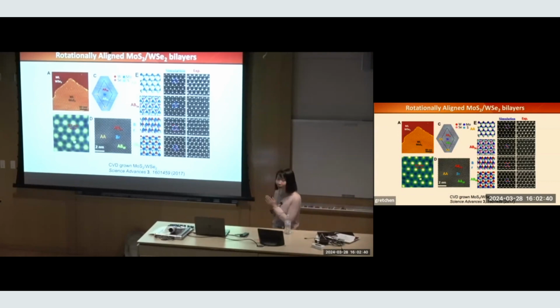But people can grow them on wafer size. And when you grow them, these two materials have different chalcogenide atoms. Because of that, the lattice constants differ from each other by a few percent. When they grow, they tend to align the crystal axes because that lowers the energy. But even when the crystal axes are aligned, because the lattice constants are different, when I shift around, the top layer and bottom layer atoms are gradually shifting. Okay? So this gives me the Moiré superlattice.